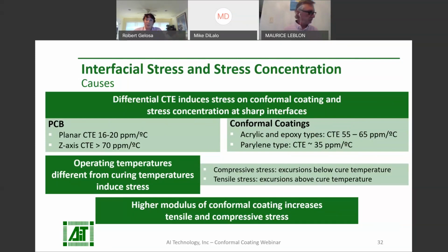With temperatures below the curing temperature of the coating, the stress is compressive. The coating shrinks more than the board. It can cause delamination from the printed circuit board, especially at sharp corners or along edges. Even worse, if the part is thin, it can cause warpage or even break the part after many cycles.